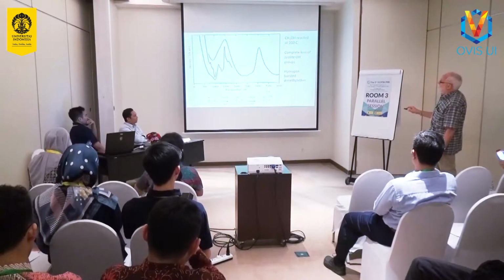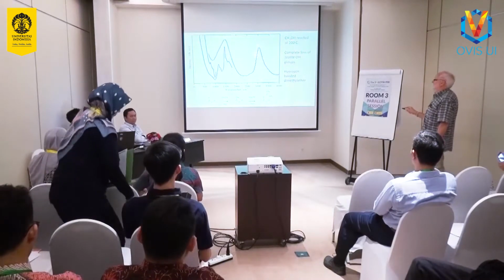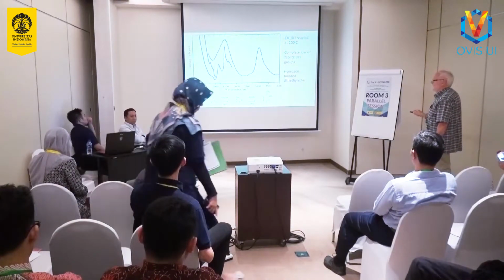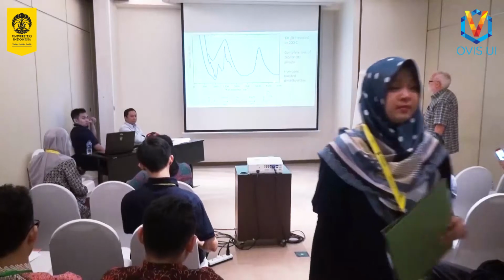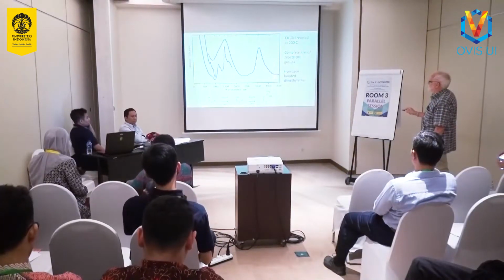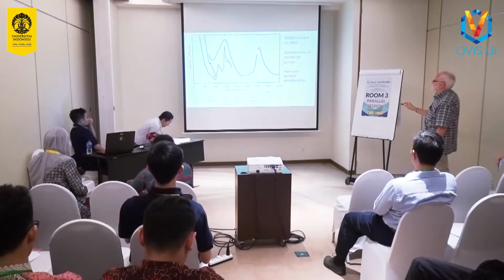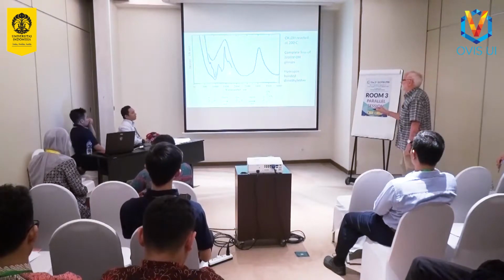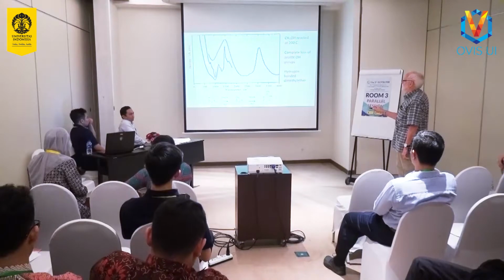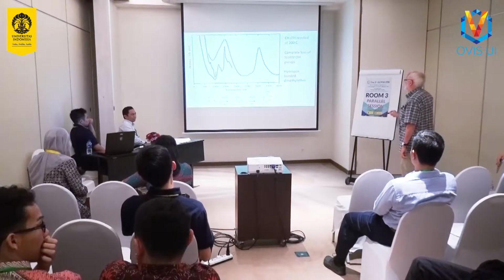And this INS spectrum we can interpret as being due to hydrogen bonded dimethyl ether. We've totally lost the zeolite OH groups, which are here. We're seeing CH stretching vibrations. Down here we're seeing CH3 bending modes, CO stretching vibration associated with dimethyl ether.